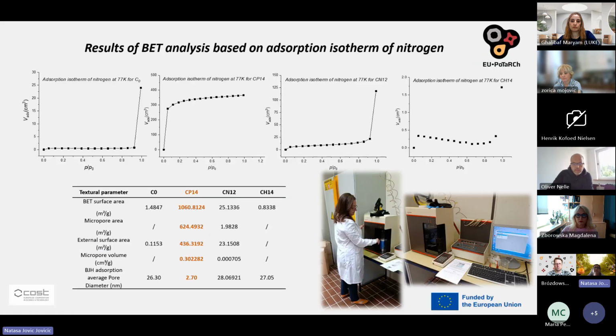Here we can see the results of BET analysis based on nitrogen adsorption isotherms at 77 Kelvin for 4 different selected biochar samples. The adsorption isotherms show clear differences in the textural properties of the materials. For example, this is the untreated, so unactivated biochar, and this is for phosphoric acid activation, sodium hydroxide, and hydrogen peroxide. The table summarizes the main textural parameters. The BET surface area of the sample activated with phosphoric acid is exceptionally high, around 1060 square meters per gram, with a significant contribution of micropores, while the starting sample and the sample activated by hydrogen peroxide have almost negligible surface area.